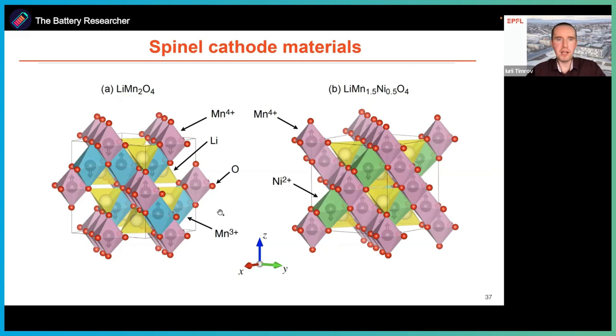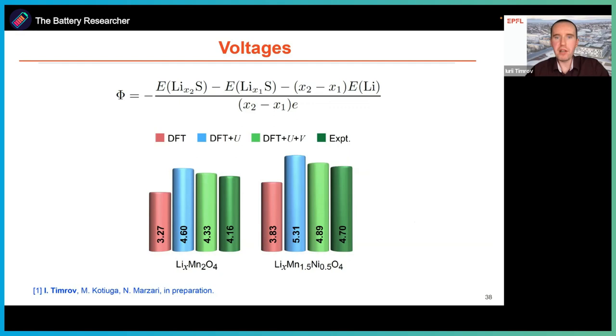The left material is antiferromagnetic, with quite complex magnetic ordering, while the material on the right is ferrimagnetic, because we have more manganese spin up, and then nickel spin down. We computed voltages for these two materials, and we again obtained similar trends: DFT underestimates the voltages largely, DFT plus U overcorrects, and DFT plus U plus V again gives the closest agreement with experiments. Though now the error is a bit larger, around 0.2 volt, while for olivines we had 0.1 volt. But it would be interesting also to study other classes of materials like layered and NASICON and others.